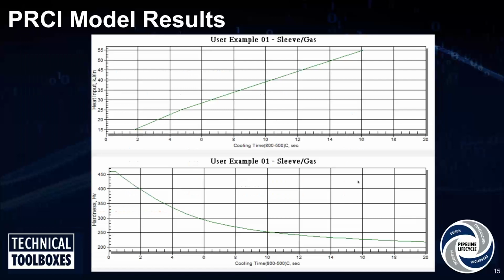The model also plots your cooling rate to hardness curves. So if your hardness doesn't show up on that table, you don't have to go back and rerun the models at different heat inputs to try to get your specific hardness limit that you need. You can go back to these plots. And the plot on the bottom predicts your weld hardness versus cooling rate. And the plot on the top predicts your heat input versus cooling rate.